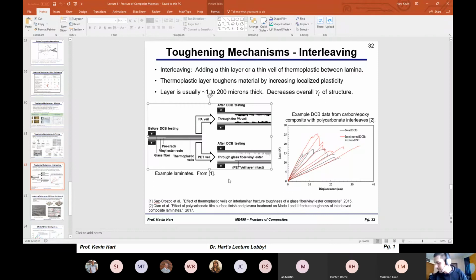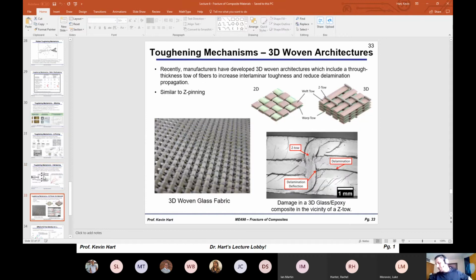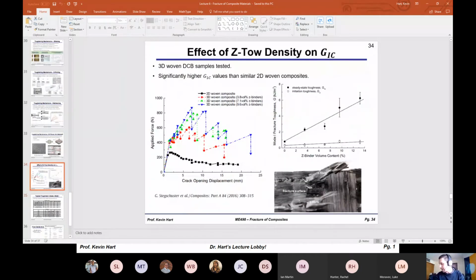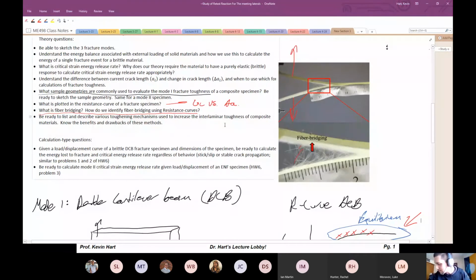Okay, so here this is a PA veil. PA is polyamide, which is another name for nylon. Here is PET, polyethylene terephthalate, which is a different type of thermoplastic that is going in between layers of a DCB. So you see it toughening the matrix. We talked about 3D composites. The through thickness reinforcement really helps to increase the interlaminar toughness of these 3D composites. So woven architectures give you this added benefit of increased fracture toughness. Those are some of the toughening mechanisms that we saw in this class.